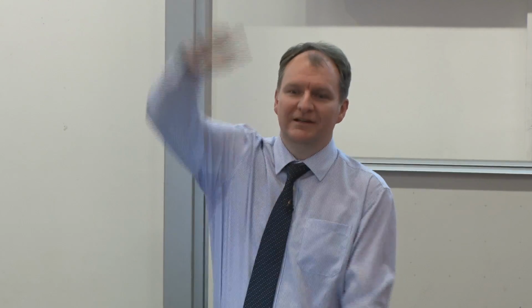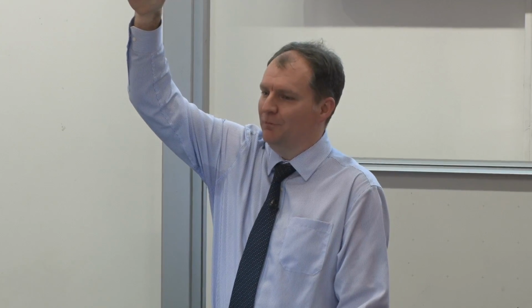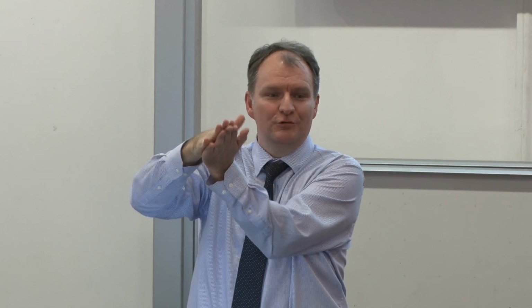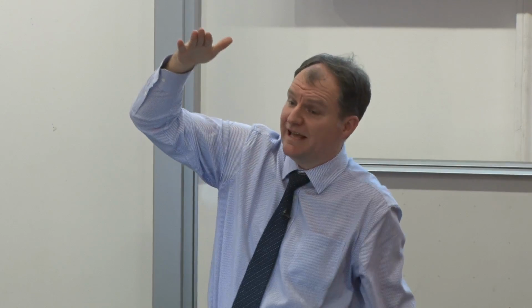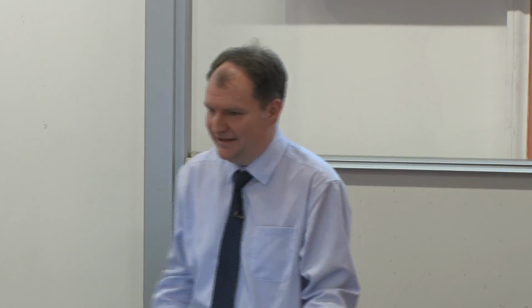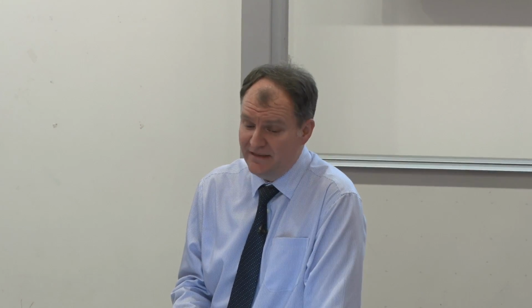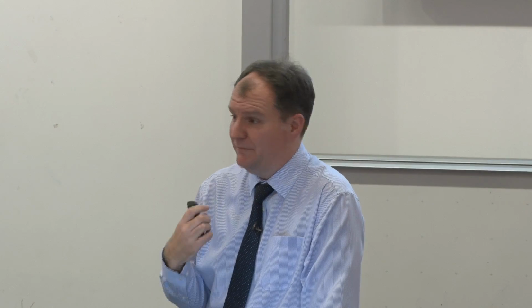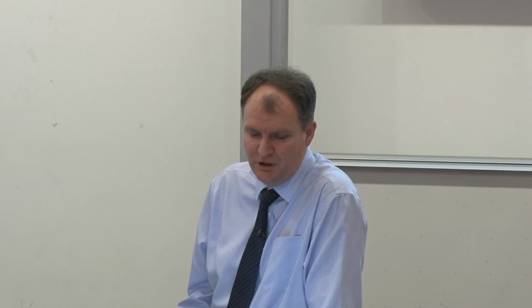The stuff you don't want will disperse upwards into the froth, so dispersion will cause you to collect stuff you don't want, and at the same time it'll cause the stuff you do want, which has been released higher up in the froth, to disperse out of the froth. So dispersion in general has a bad effect on the performance of your system. And again, it's one of these things which nobody had actually measured. So we needed to consider dispersion, and there are two main dispersion mechanisms in flotation.